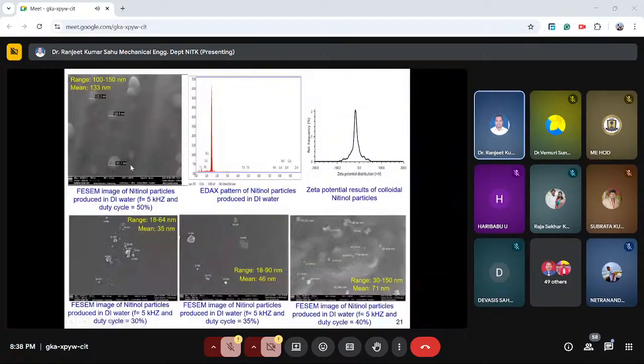You see the results here. This result shows the field emission scanning electron microscope images of nitinol particles produced in DI water. We found the size of the particles to be 100 to 150 nanometer, with a mean size of 133 nanometer. The EDAX pattern shows the nitinol nanoparticles with negligible impurities at a frequency of 5 kilohertz and 50% duty cycle. The zeta potential results also show that the dispersion stability is a little bit poor here.